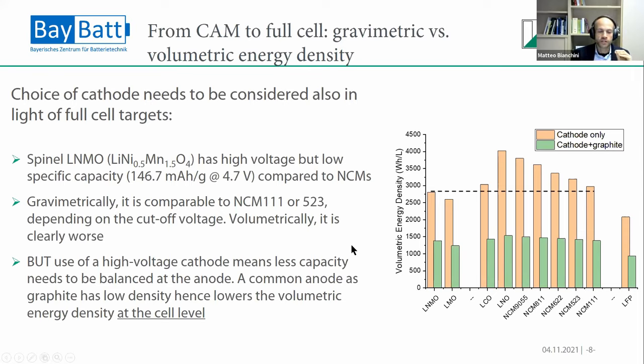However, if you consider the fact that, of course, you need also a negative electrode, you need an anode, which, to make it simple, the most well-known and most used anode today is graphite. The graphite is a low density. So when you consider, not the full cell level here, what I have in this plot is actually the two electrodes. In LNMO, since you have a lower capacity, so the high energy is brought to you by the high voltage, not by the capacity, then you don't need to balance this capacity with a lot of graphite at a negative electrode. Therefore, you will not be hit negatively in your cell level performances by the presence of this graphite.